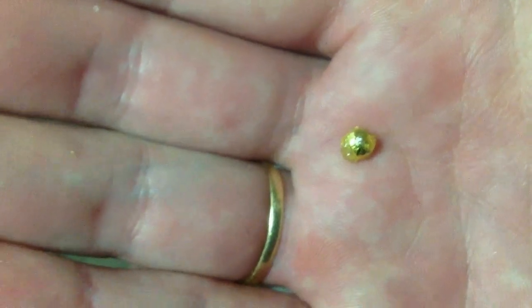Alright, that's all for now. I just thought I'd better quickly show the mercury we recovered — it's just in the same pan with the slag. We actually had to smash the retort a little bit to get it out. We didn't get it come out the end pipe; it stayed up in the top, inside the pipe. It seems a very flawed retort we've got — both times we've used it now we haven't actually had any mercury coming out; it just gets lodged in the pipe, which does not seem right. So that should be all for now.